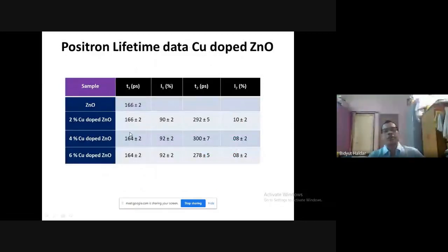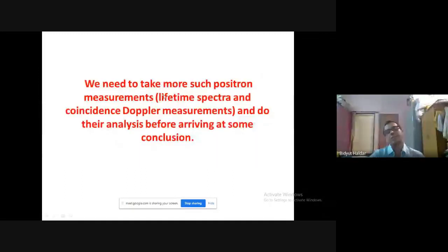Our positron lifetime data are tabulated here. We are in the process of analyzing these data. You can see there are two lifetimes, tau1 and tau2. This is of the order of 166 picoseconds, and this is of the order of 292 picoseconds, with their corresponding intensities, for the different samples that we have. I would like to say that we need to take some more positron measurements, especially lifetime spectra and coincident Doppler measurements, and do the analysis before arriving at some conclusion.